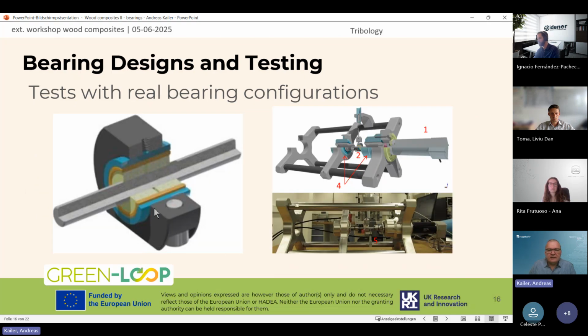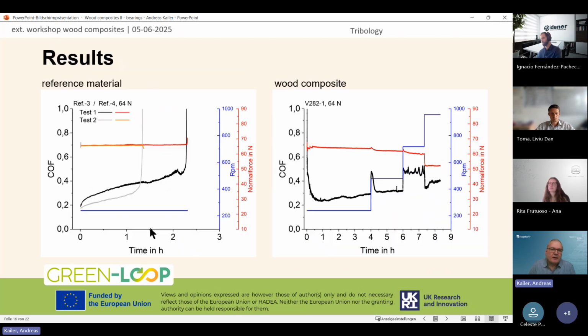Here you can see a photograph and the testing geometry as a sketch. And here you can see results on the left-hand side. We used reference materials. So this is not a wood composite, it's a thermoplastic material. And you can see the black and gray curves are the friction coefficients.